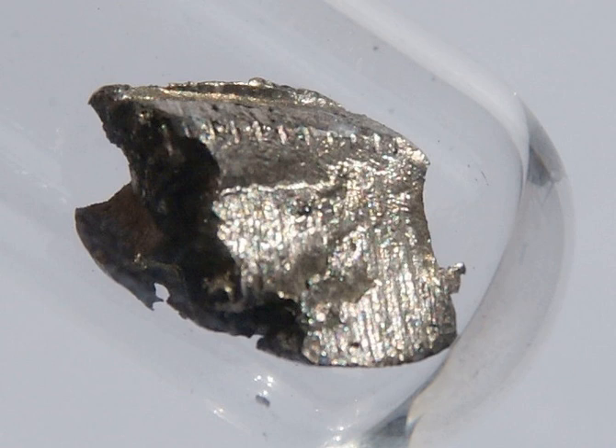Bastnäsite, LnIIICO3F, is usually lacking in thorium and the heavy lanthanides beyond samarium and europium, and hence the extraction of cerium from it is quite direct. First, the bastnäsite is purified, using dilute hydrochloric acid to remove calcium carbonate impurities. The ore is then roasted in the air to oxidize it to the lanthanide oxides. While most of the lanthanides will be oxidized to the sesquioxides Ln2O3, cerium will be oxidized to the dioxide CeO2. This is insoluble in water and can be leached out with 0.5 M hydrochloric acid, leaving the other lanthanides behind.